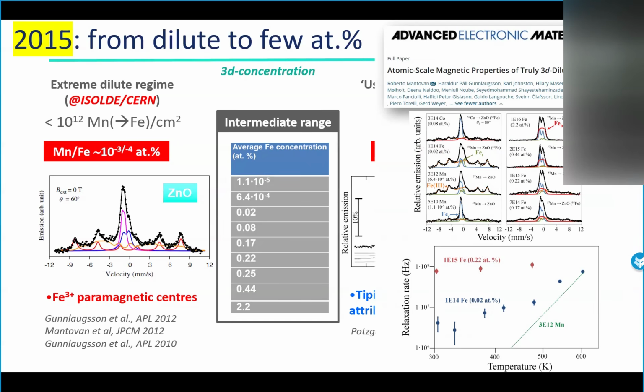And gradually you move to a temperature-independent process, which to us was the signature of the first spin-spin relaxation, meaning that your iron 3+ start to form the very early formation of clusters. And look at that. That was happening at 0.2 atomic %. So we were tracking somehow live the gradual transition from the ultra-dilute slow relaxation center to spin-spin relaxation, due probably to the formation of clusters.